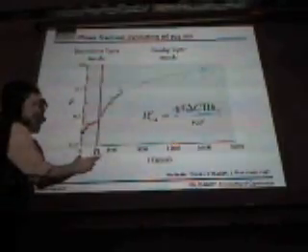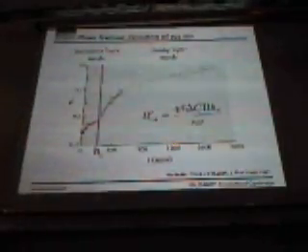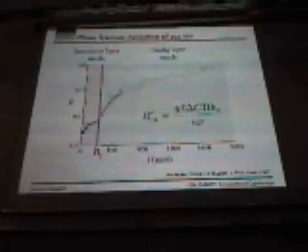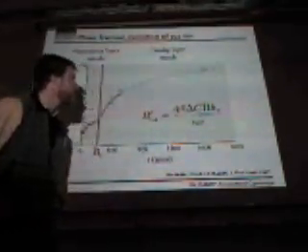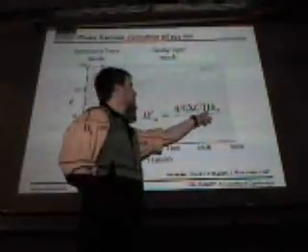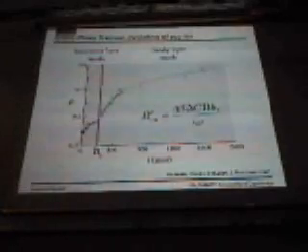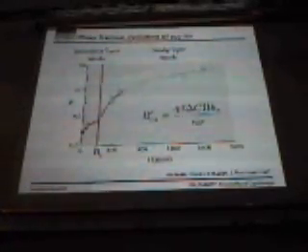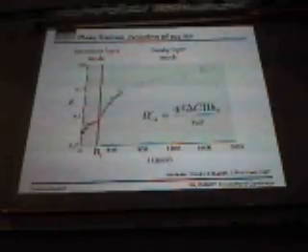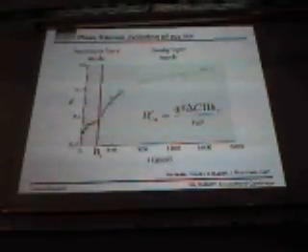Once it's grown to a critical thickness, HC, you can achieve a critical Rayleigh number, again given by this sort of combination where the permeability and this critical height play a key role. And once that critical Rayleigh number is exceeded, you can actually get this convection within the ice, and that dramatically changes the phase fraction. As we saw before, you get these chimney-like structures, which are regions of zero solid fraction.